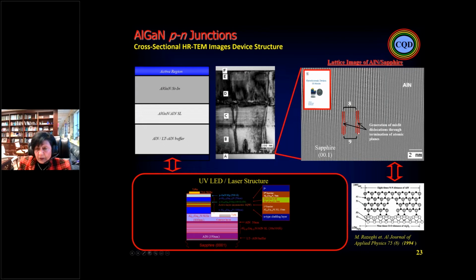Here we have the sapphire substrate, that is the work of two of my students, Alireza Yasan and Ryan McIntosh, as you can see here, with the transmission electron microscope done at Northwestern in Professor Dravid's group. Sapphire substrate is wurtzite. Aluminum nitride is wurtzite. But there is lattice mismatch. Every 9 planes of sapphire is equivalent to 8 planes of aluminum nitride. And when you are growing one over the other, you have a 30 degree lattice turning by comparison to the substrate. As you can see here, every 9 planes, we have one edge dislocation.